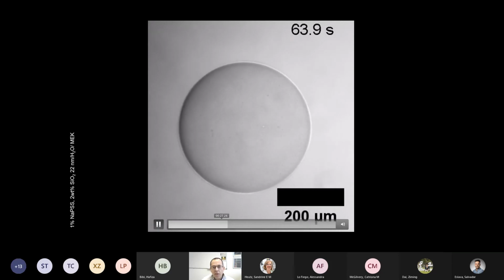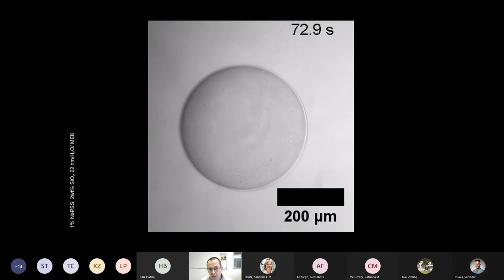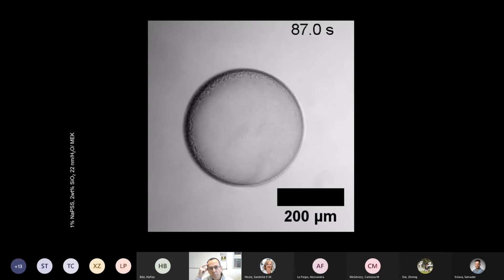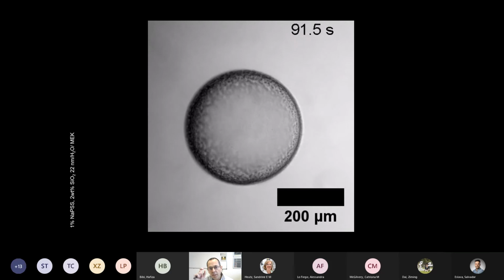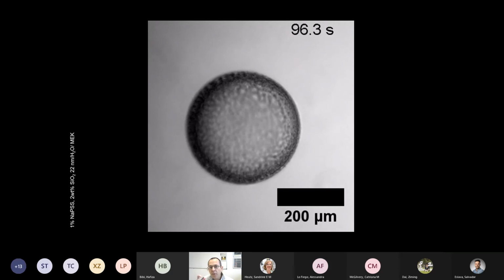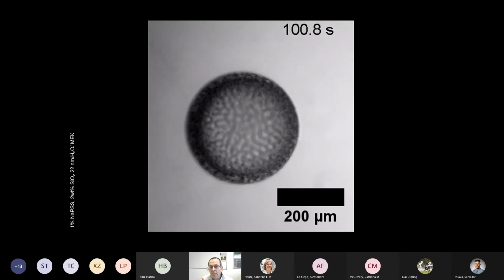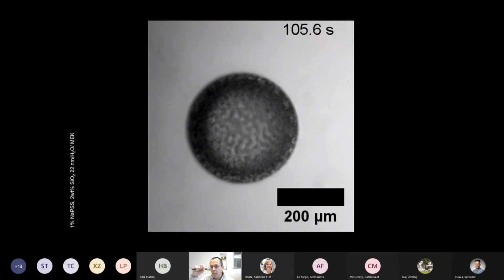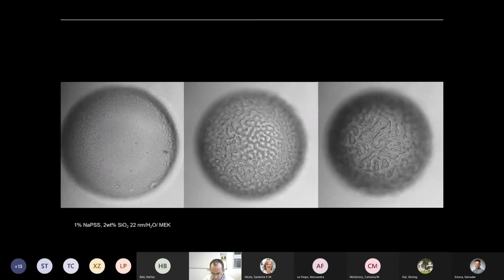The texture of this particle is going to become the characteristic of a spinodal. You see that you have a selection of a specific length scale, and you see what looks like a brain-like structure with a well-defined length scale. This is important because it gives us the interconnectivity that we think we need for certain release profiles. So that's a zoom in into that brain-like structure that coarsens over time until it eventually solidifies.